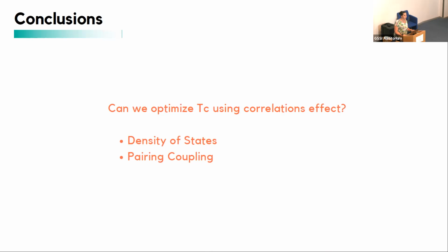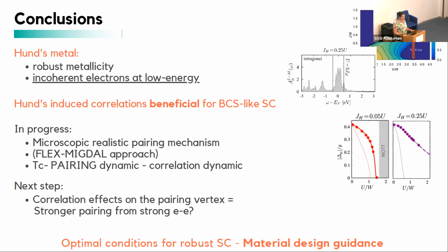The open question was, can I include correlation effects and see if they enhance the density of states at the Fermi level and the pairing coupling? So the answer is that I showed you that the Hund's metal is a robust metal and has a lot of incoherent electrons at low energy. So essentially the answer is that the density of states close to the Fermi energy is higher in the Hund's metal. And this is extremely important and beneficial for superconductivity.